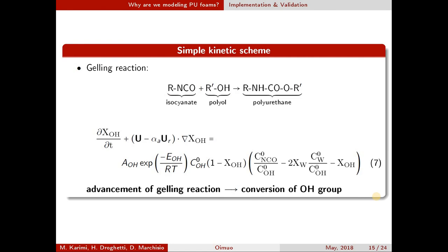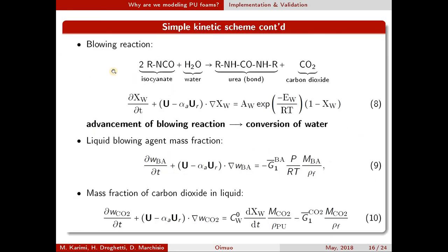For the kinetics, we applied a rather simple kinetic scheme. We include the gelling reaction by adding a PDE with a customized source term for the conversion of the OH group, which tells us about the progress of the gelling reaction. The next one is the blowing reaction — a similar approach has been taken, following the conversion of water. And two more PDEs are included for the amount of blowing agent and CO2 in the foam.